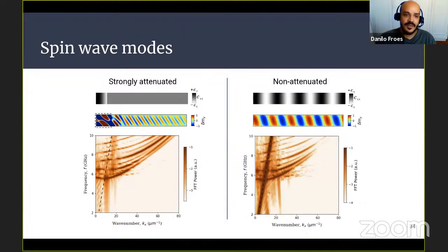So we're obtaining the spin wave modes for two extreme cases. One where the acoustic wave, the strain wave, is strongly attenuated, so it just happens here at the beginning of the stripe and then rapidly dies. And the non-attenuated case, in which the strain excitation goes all the way to the end of the stripe. This non-attenuated case would typically be the one we would obtain experimentally, because these acoustic waves propagate on the order of millimeters.